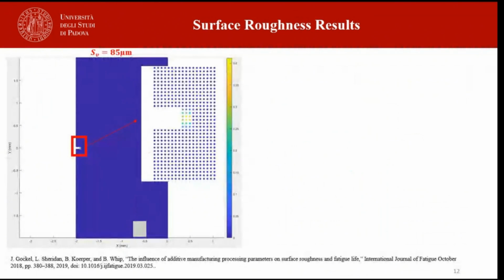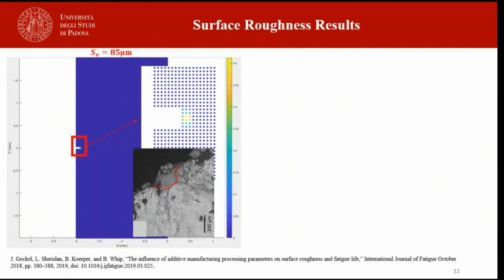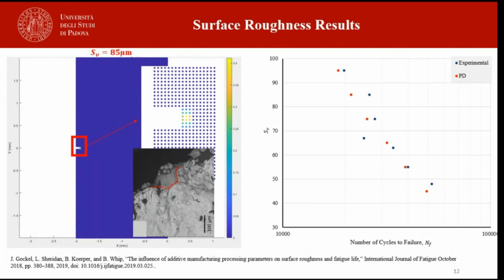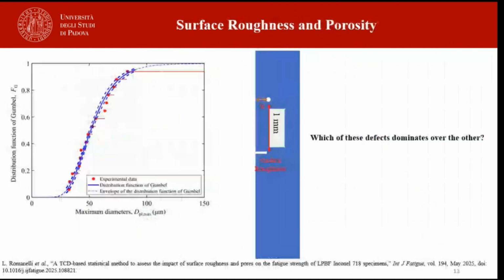This figure is the result for the case with the maximum depth of 85 micrometers. As we can see, the crack nucleates from the surface roughness sites, which is in strong agreement with the experimental results. This graph compares our results with experimental. The y-axis is the maximum depth of surface roughness, and the x-axis is the number of cycles to failure. As you can see, our peridynamic results are in good agreement with the experimental ones.